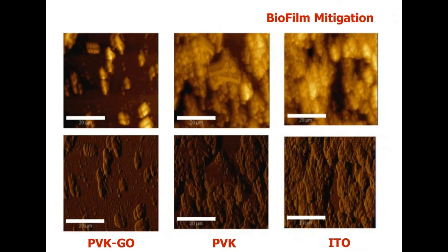Lastly, where does AFM fit in? So here is a nice AFM image showing the PVK GO when present as a film actually prevents biofilm formation, and where we have PVK and ITO as a film without graphene oxide, we see lots of bacteria populating and growing as a healthy biofilm. So in this case, AFM non-contact mode allowed us to visualize firsthand, morphologically close, the presence of biofilm without the graphene oxide. So with that, I'm ready to close.